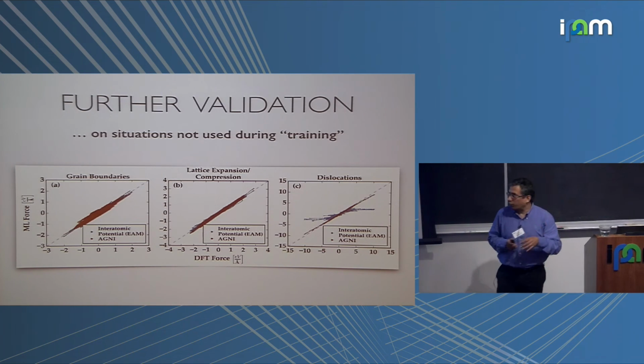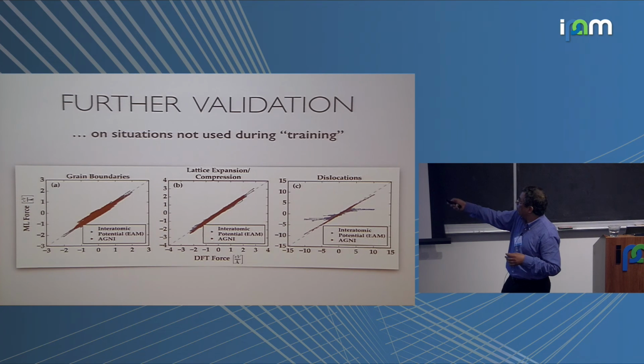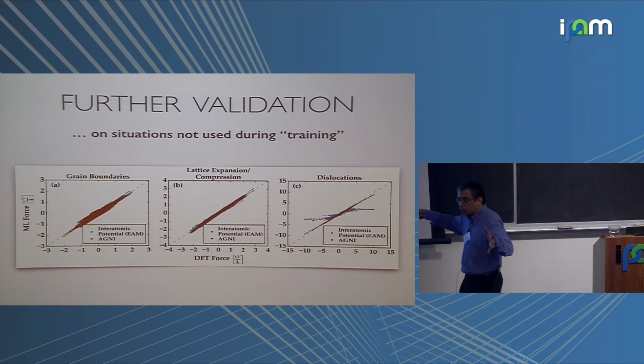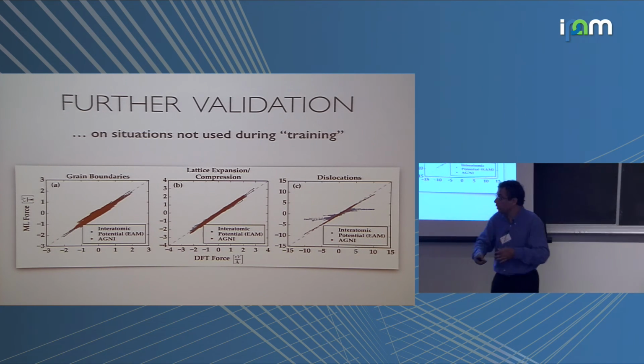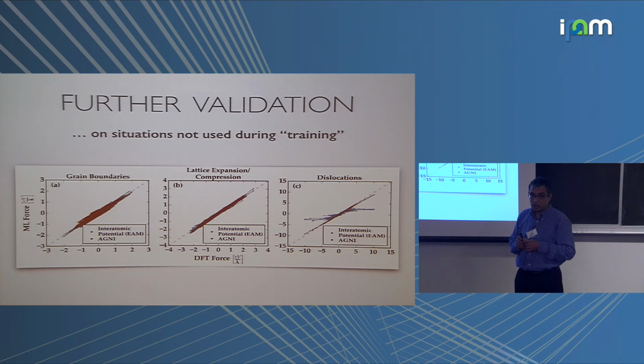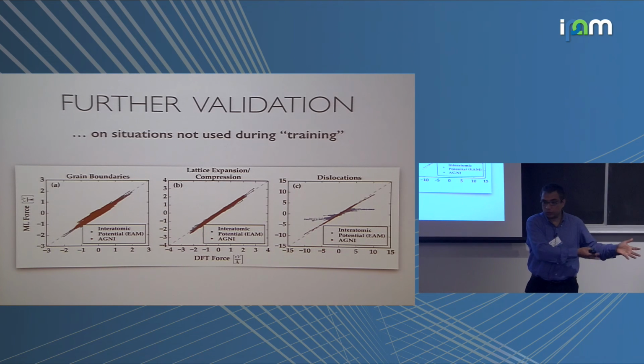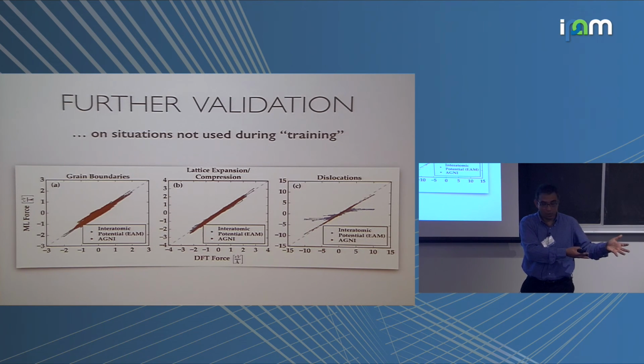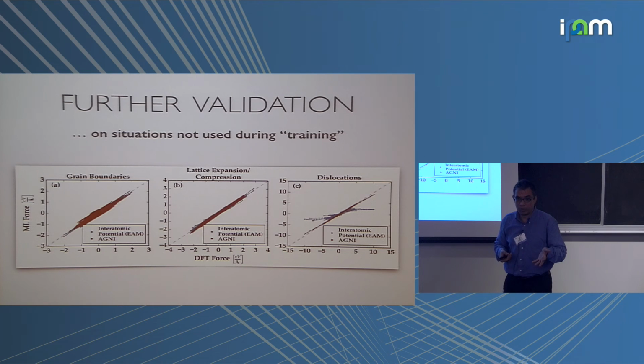Okay. So now we subjected the force field to other tests. Further validation on situations not used during the training, not used during the construction of the force field. We considered three scenarios: grain boundaries in aluminum, expanded and compressed situations in aluminum, and an edge dislocation. When we do this, we also wanted to compare how the force field is performing with respect to DFT, but also with respect to a very well understood, very well accepted force field for aluminum, which is the embedded atom method.